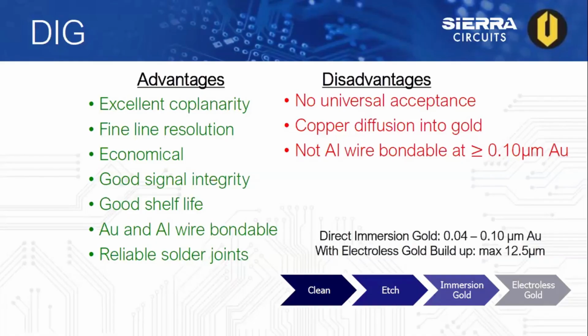Now, some disadvantages are that it is not universally accepted, has seen copper diffusion into the gold, and it is not aluminum wire bondable at greater than or equal to 0.1 gold microns.